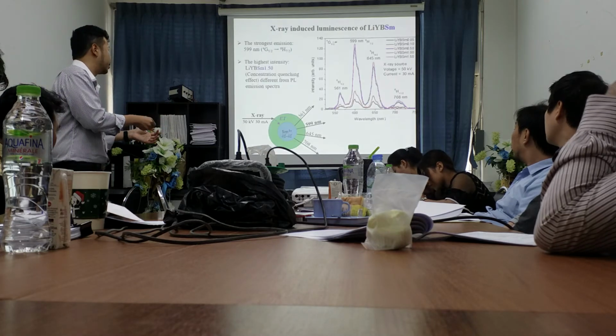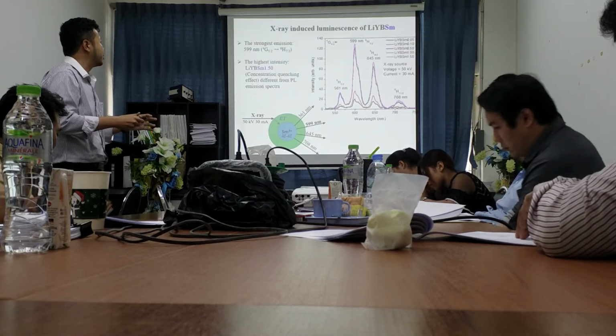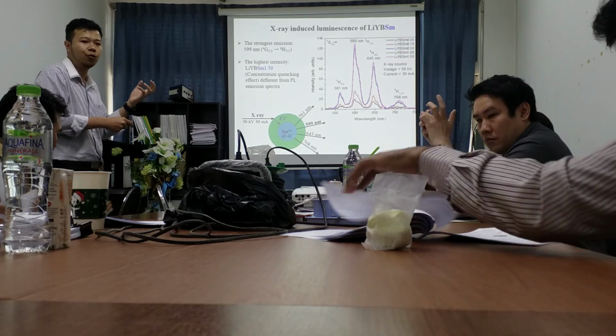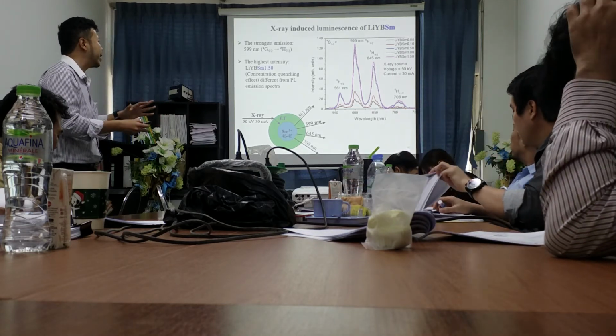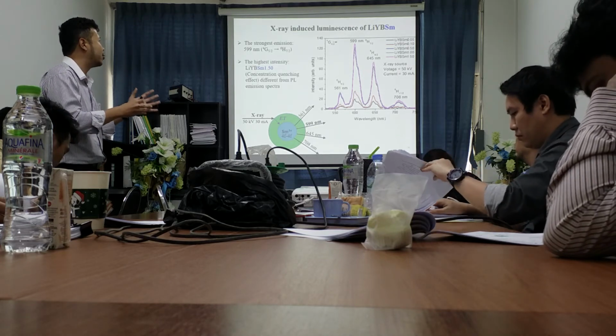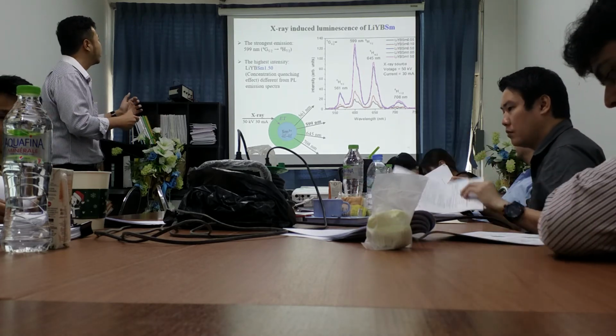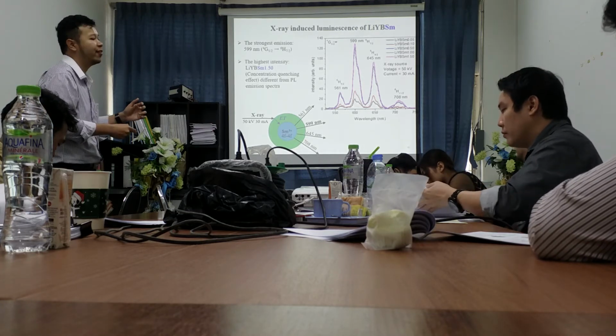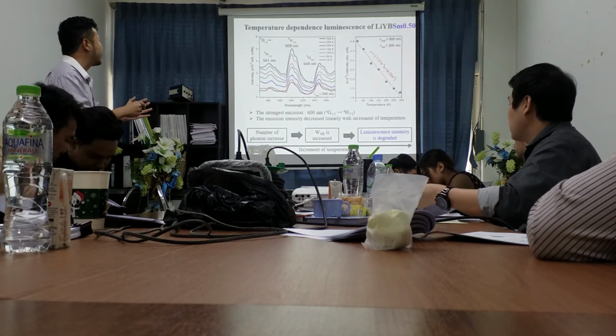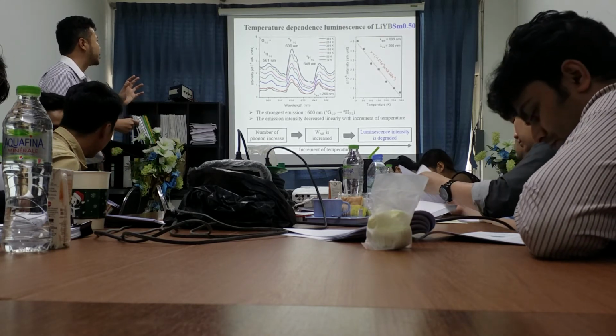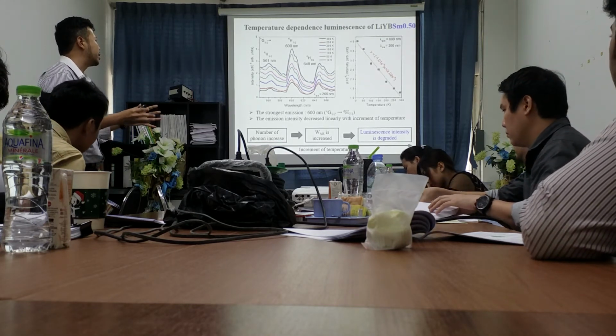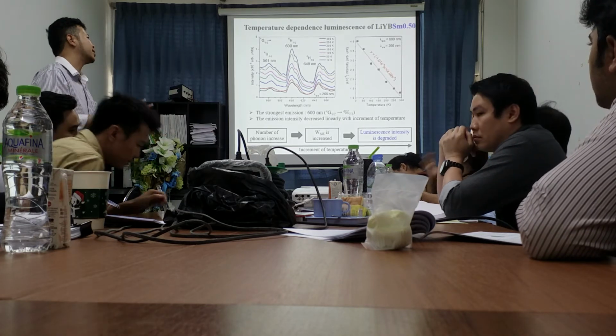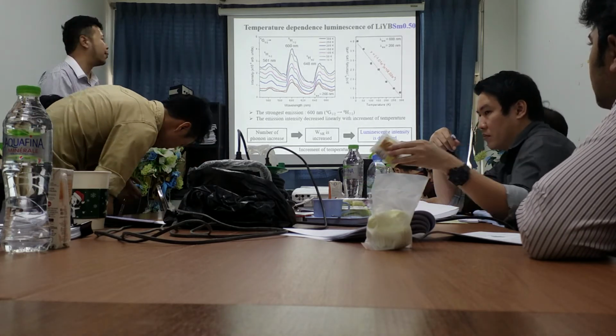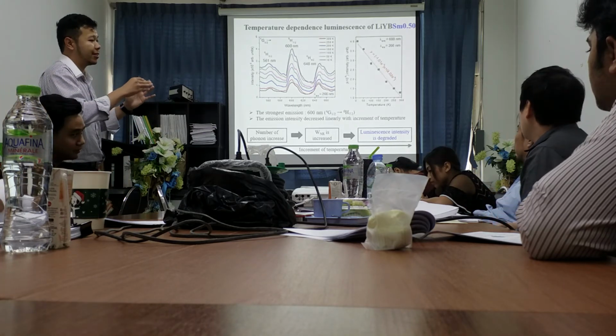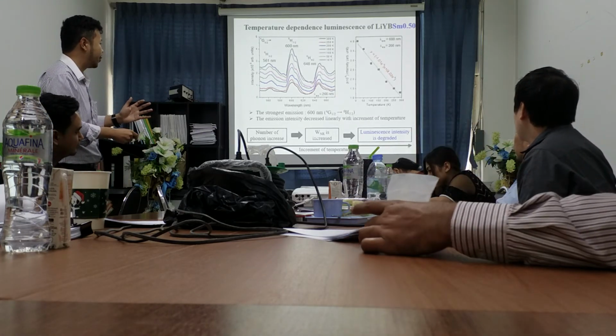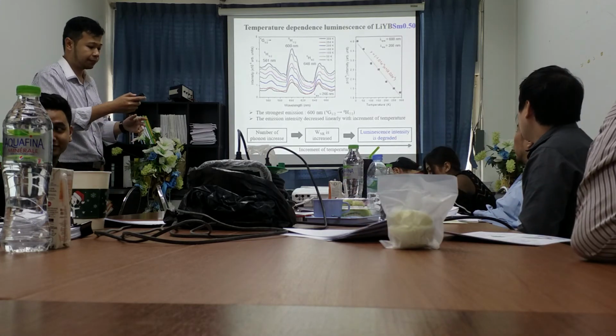Next, X-ray luminescence shows the same pattern as the photoluminescence emission spectra. The difference is the quenching, because for the X-ray luminescence, the quenching occurs in the Sm glass with 1.5 mole percent. For the temperature-dependent luminescence, we found emission peaks similar to the photoluminescence emission spectra and the same reason for the luminescence intensity decreasing with increasing temperature. It is due to the phonon increase.